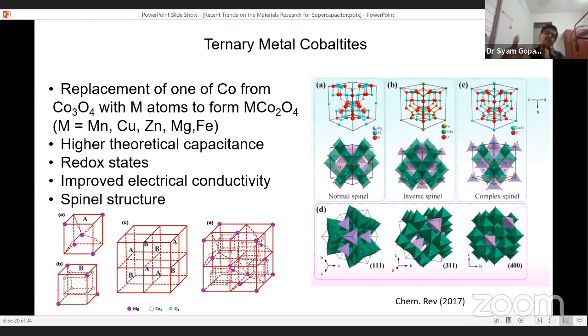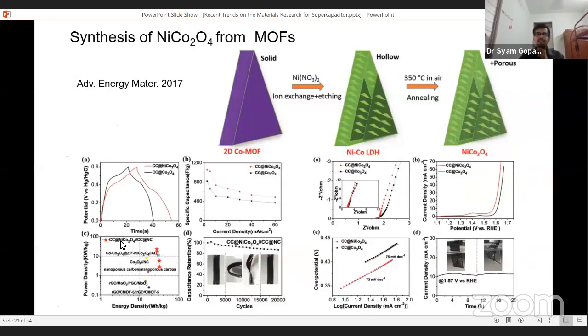Then our research again focused, rather than on cobalt oxide, on ternary metal cobaltates, where we tried to substitute one of the cobalt atoms from the ternary sites of this particular material with metals like manganese, copper, zinc, magnesium, as well as iron. And its theoretical capacitance, redox states, as well as conductivity and spinel structure could improve the result.